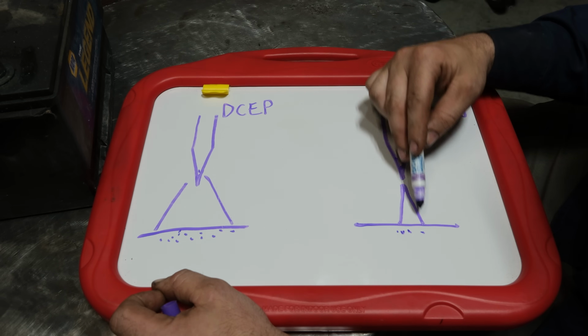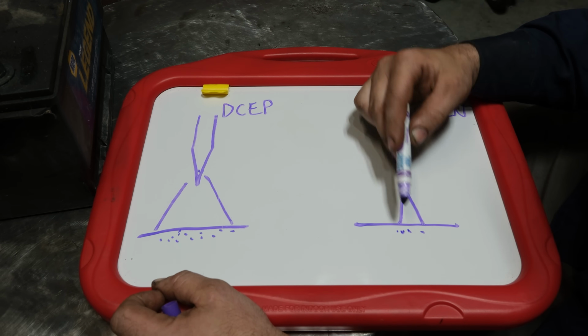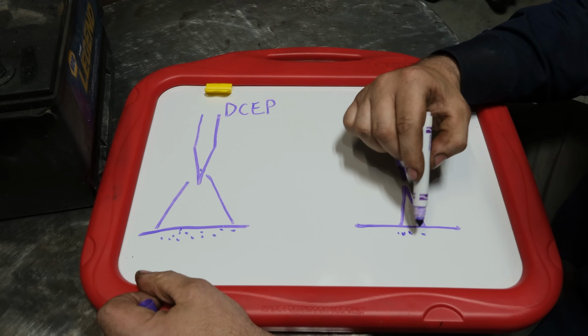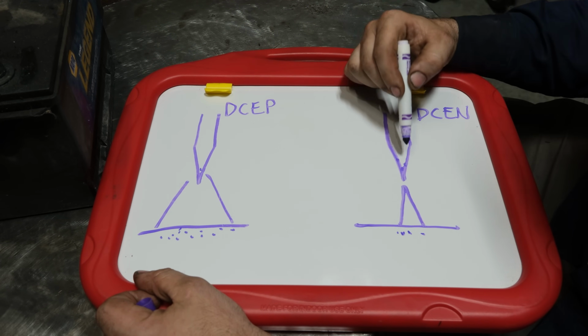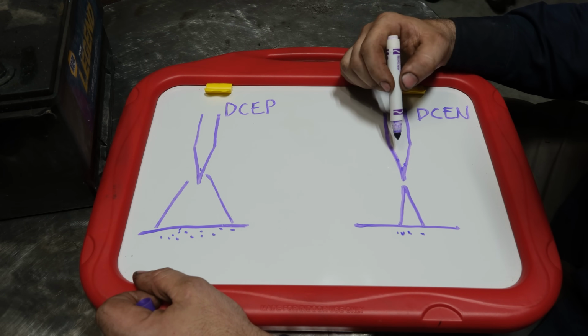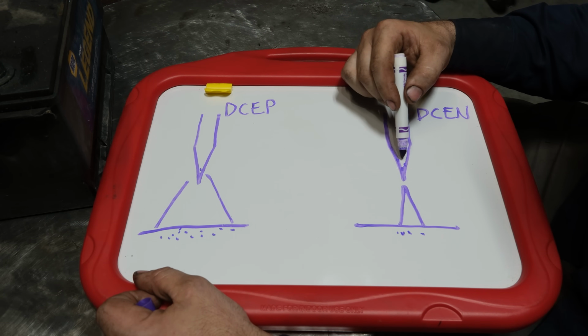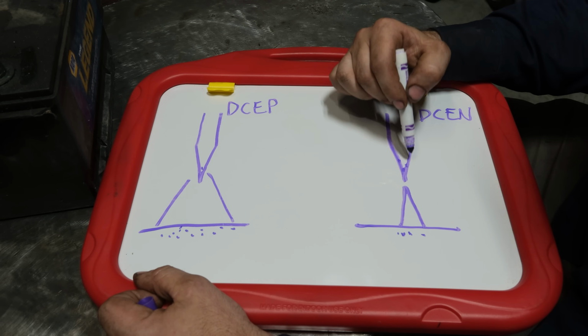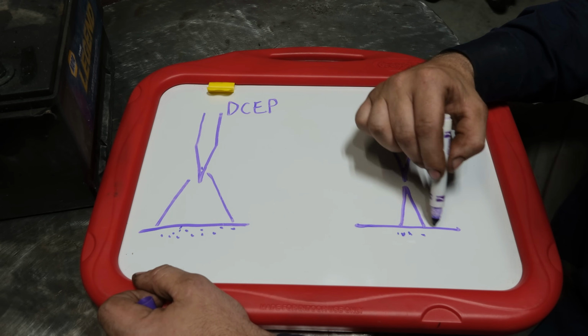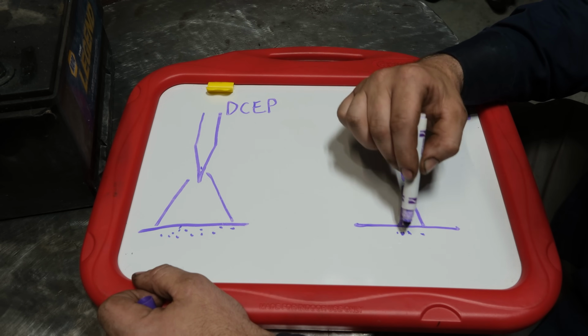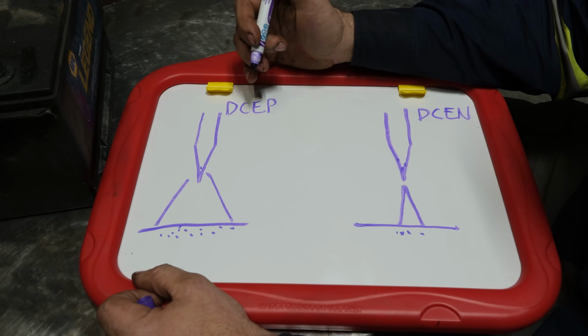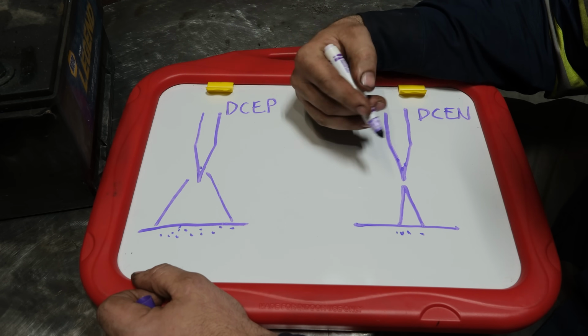The fact that those electrons are striking your base material, and that impact force puts a lot of heat here rather than on the tungsten. That is why on electrode negative, the tungsten is able to handle significantly higher amperage than on EP and not melt: the heat of the impacting of the electrons is down here. Now, the polarity has far more effect than just that.